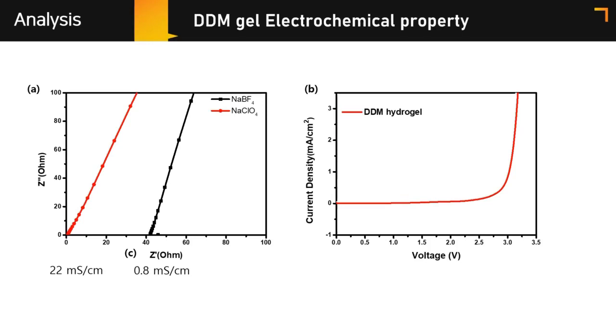This gel is tested in a water-in-salt solution, 15 molar concentration NaClO4. Graph A is EIS data for explaining ionic conductivity. In this graph, the red line is the gel soaked in ClO4 solution, and the black line is the gel soaked in BF4 solution. The ClO4-soaked gel has high ionic conductivity, 22 millisiemens per centimeter. It shows significantly higher ionic conductivity than other polymer gels.